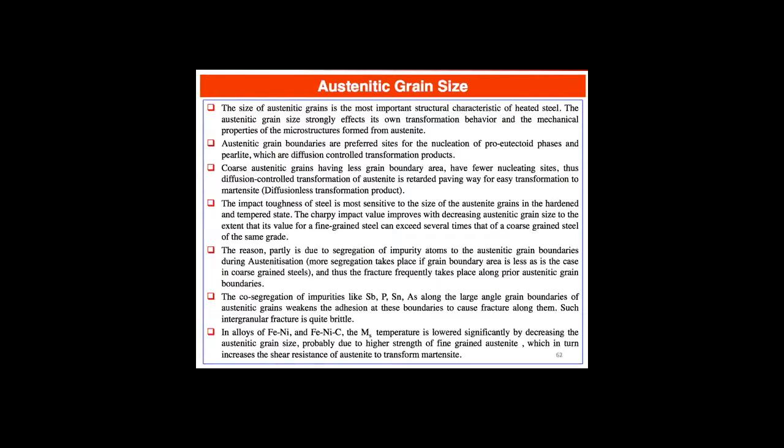And then in alloy steels, we have segregation of elements to the grain boundaries in the austenite phase that weaken the interfaces, right? And when we transform either to martensite or then temper, these alloying elements tend to stay at the prior austenite grain boundaries and give us short circuit fracture paths.